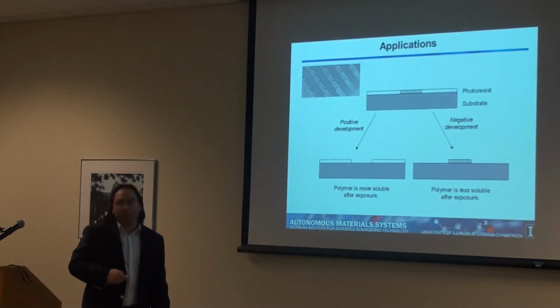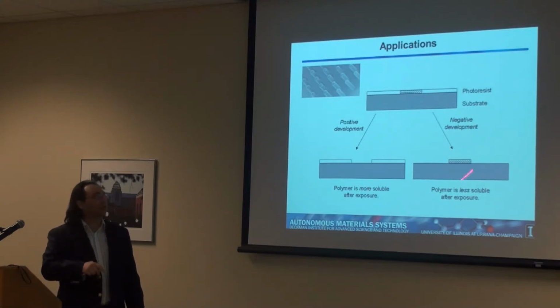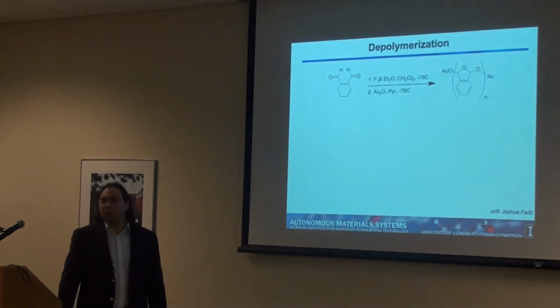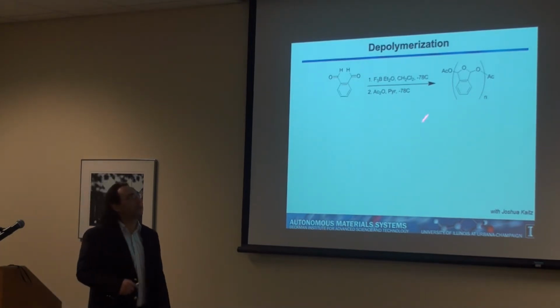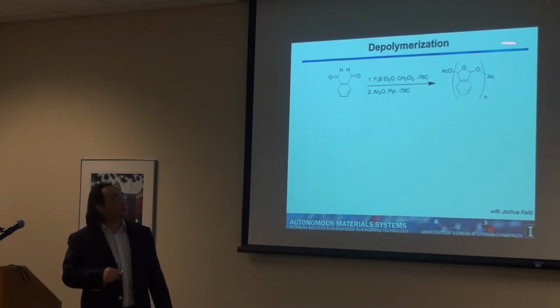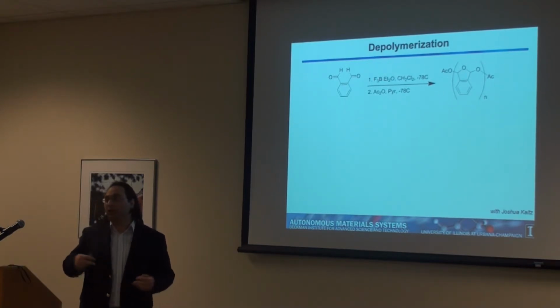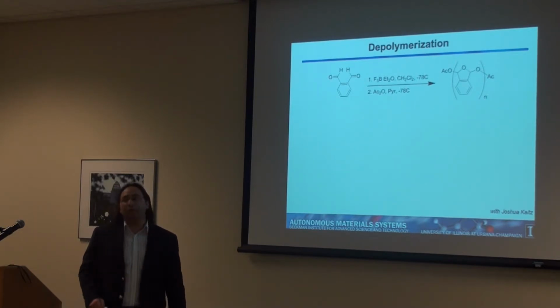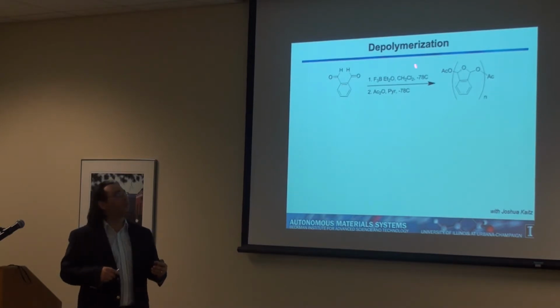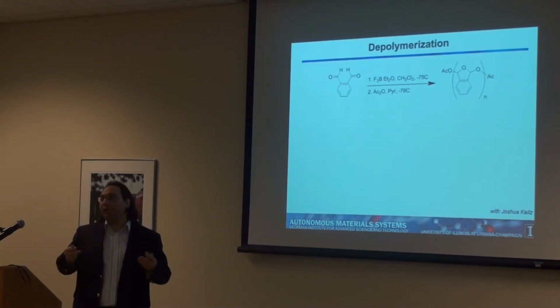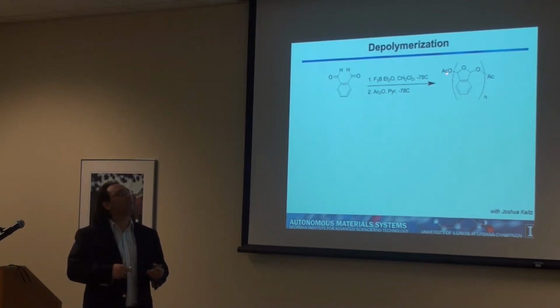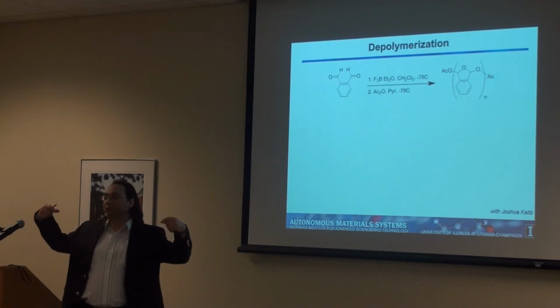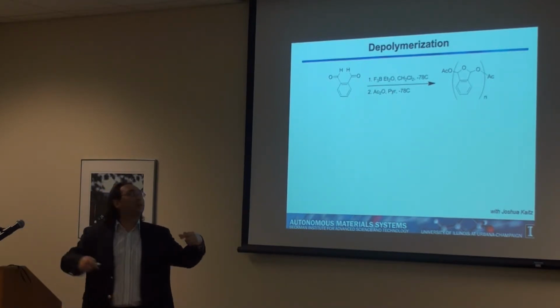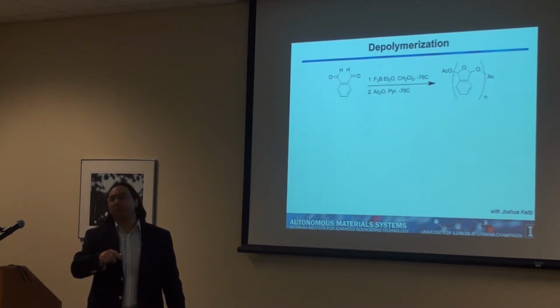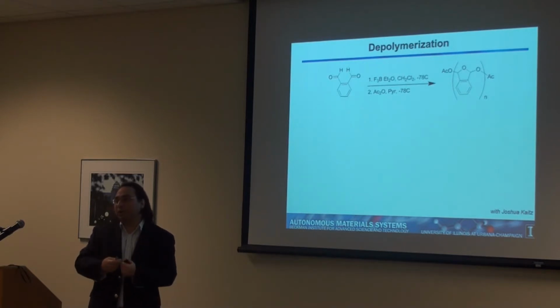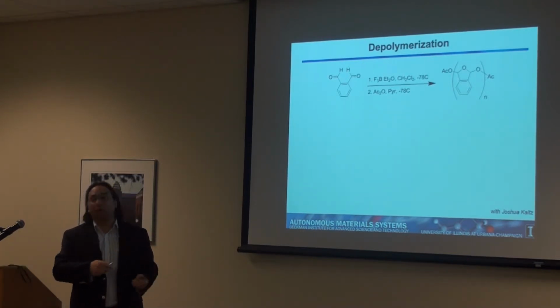So I'll just talk a little bit about this type of system, which is much easier to work with than this one. One of the most commonly used polymers for positive photoresist is called PPA, polyphthalaldehyde, which is this polymer. You have this repeating unit in your material, and this polymer is very interesting because if you just polymerize it, and the polymerization is done at very low temperature, when you heat it up, it will already depolymerize, unless you end cap it. You add chemical groups at the ends that cap the polymer on both sides. So basically, it's a very interesting polymer: if you remove one of the end caps or break any bond in the middle of the polymer, it will completely depolymerize and go back to this monomer.